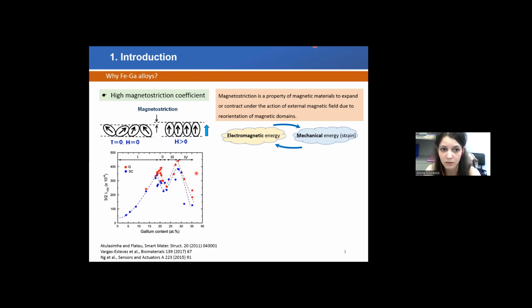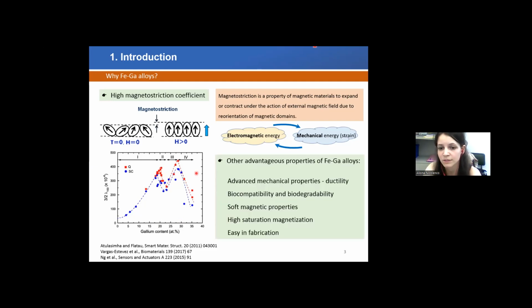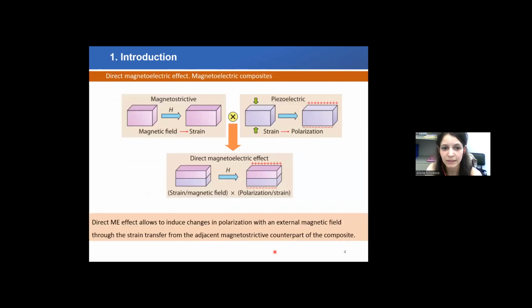Among the other interesting properties of these films are their mechanical properties, such as ductility, for example, biocompatibility and biodegradability. In terms of magnetic properties, they have soft magnetic behavior and high saturation magnetization. And well, last but not least, they are easy to fabricate, especially when you compare them to some other magnetostrictive materials that are quite difficult to fabricate. So due to this number of interesting properties, iron gallium alloys recently became interesting for the fabrication of so-called magnetoelectric composites.